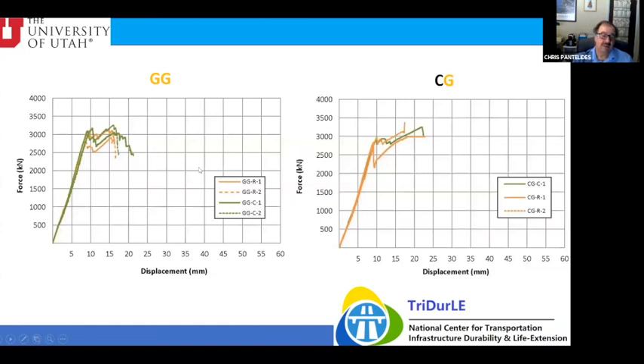This is the all fiberglass, and something we didn't expect, we actually see some drop in the peak load capacity and the displacement capacity of the ones that were exposed to water, which means even though this is all fiberglass, it seems like the water actually can do some damage to the fiberglass.